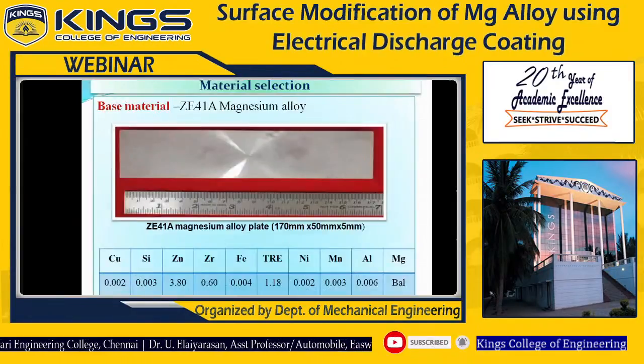This is the material selection, and this is one of the magnesium alloys. Base material ZE41A magnesium alloy. What does Z mean? Zinc. E means rare earth. Zinc 4%, rare earth 1%. A is the first series of magnesium alloy. This is the workpiece used for our research, with dimensions 170 mm length, 50 mm breadth and 5 mm thickness. ZE41A magnesium alloy has been used.